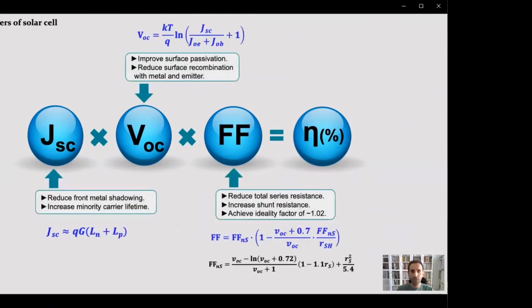To increase the short circuit current, we need to reduce the front metal shadowing and increase the minority carrier lifetime. Open circuit voltage is a function of short circuit current and can be increased by improved passivation and reduced recombination. Fill factor is a function of open circuit voltage, series resistance, and shunt resistance. To achieve high fill factor, we need to reduce total series resistance and increase the shunt resistance.